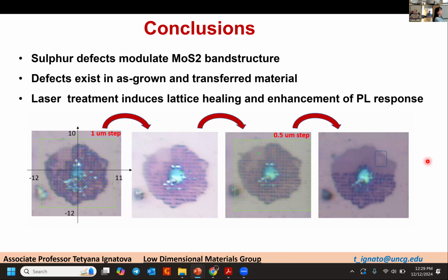So one thing that would be beneficial is to really identify contributing factors to the change in the PL. I mean, it's no surprise that you're changing the PL with the laser. But you want to be able to attribute that to a specific defect or whether it's desorption of a gas. If you can do it in vacuum, that's the most ideal. Or if you do it in an environmental chamber where you're purging it with very dry air or nitrogen, argon would be preferable. That would maybe help to isolate what is actually happening as a function of laser irradiation.